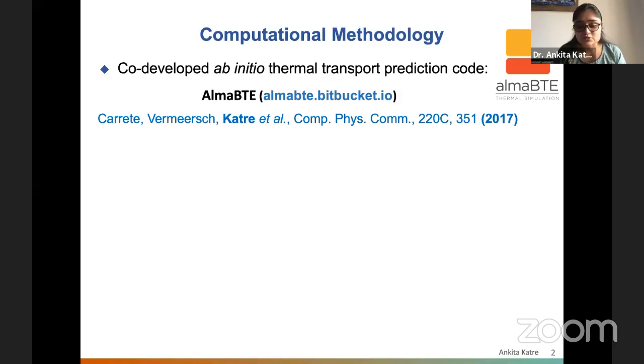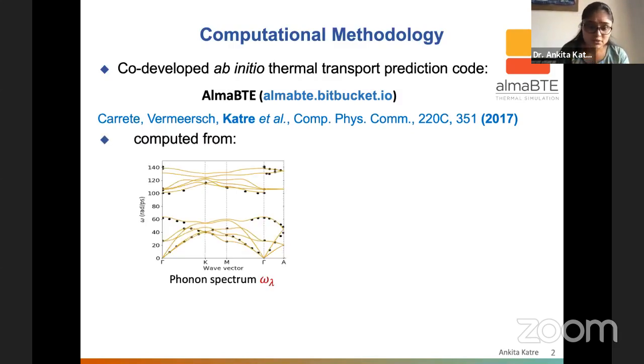What we follow is based on the solution of the Boltzmann transport equation, with some approximations for sure, to calculate the thermal conductivity. This has been implemented in the code ALMA-BTE, which I co-developed in my previous group. Coming back to the term ab initio, what is done in this code is that the thermal conductivity is calculated by considering the contributions of each and every phonon mode.